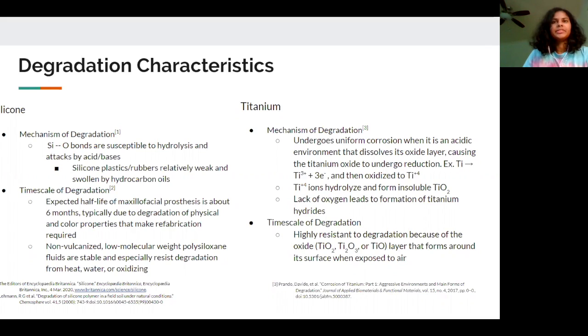Titanium undergoes a uniform corrosion when it's in an acidic environment, which dissolves its oxide layer, causing the titanium oxide to undergo reduction. Reduction produces titanium plus 4 ions that hydrolyze and form insoluble titanium dioxide. When there's a lack of oxygen, titanium hydrides form. Titanium doesn't really have a timescale for degradation because it is so highly resistant to corrosion because of its oxide layer that forms around its surface when it's exposed to air. Like titanium, silicone is quite resistant to degradation, but components tend to get replaced periodically to maintain a high level of performance and to minimize already rare occurrences of degraded material associated toxicity. Unlike titanium, silicone does not evenly degrade due to its amorphous nature.